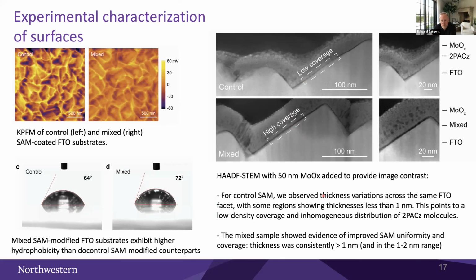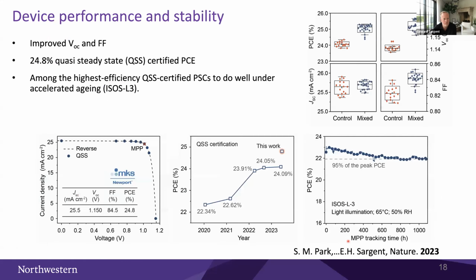And the most striking thing was that there were times in the absence of the new SAM technology where the thickness fell below a nanometer. But when we used the mixed SAM approach, the thickness was always greater than a nanometer and typically in the 1 to 2 nanometer range.